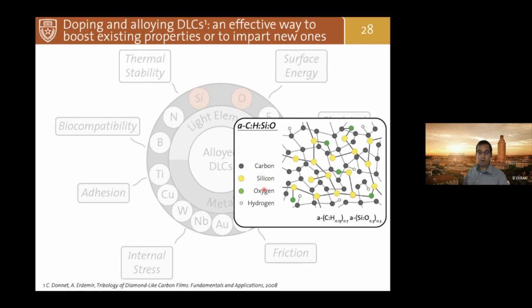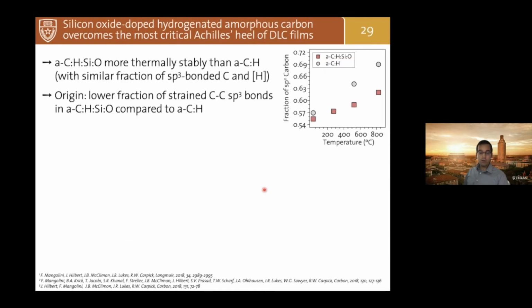We call it amorphous hydrogenated carbon with silicon and oxygen. And we have done extensive work in the last five years looking at these. So we coupled advanced characterization methods that synchrotron facilitates, including NEXAFS spectroscopy, X-ray absorption spectroscopy, and molecular dynamics, trying to understand the origin behind the higher thermostability of this material compared to the material without silicon and oxygen.